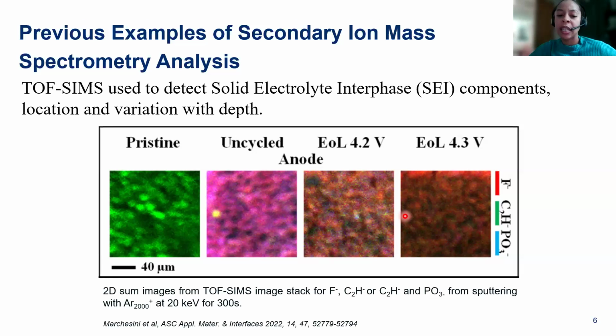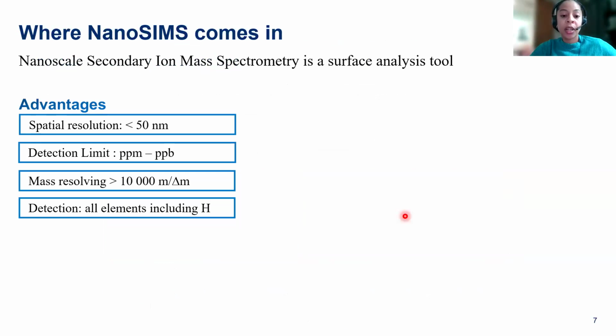But what we don't really see is very high detail and morphology in the material. So that led me to ask the question, how can we get spatial resolution and similar types of information? That's where the NanoSIMS comes in, which is another surface analysis tool, a nanoscale secondary ion mass spectrometer, and it has a spatial resolution of less than 50 nanometers. It also has a really good detection limit down to the ppb for some sample types, very high mass resolving power, and we can detect all elements, including hydrogen.